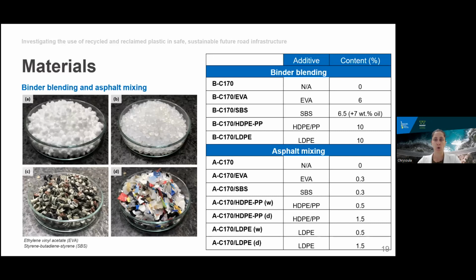We prepared 4 blends, plus the unmodified C170, which we then used to compact 5 slabs via the wet method, and then we made another 2 slabs, adding the plastics through the dry method. For simplicity in these presentations, we discussed the wet method where additives and modifiers are incorporated during the binder blending process, and that's before mixing with the aggregates, and the dry method where additives are incorporated with the aggregates during